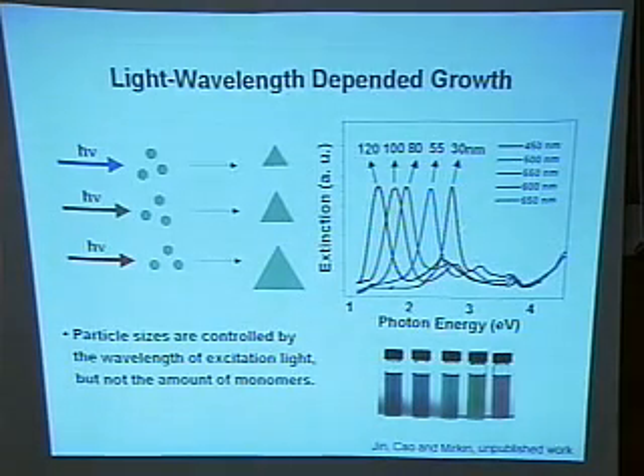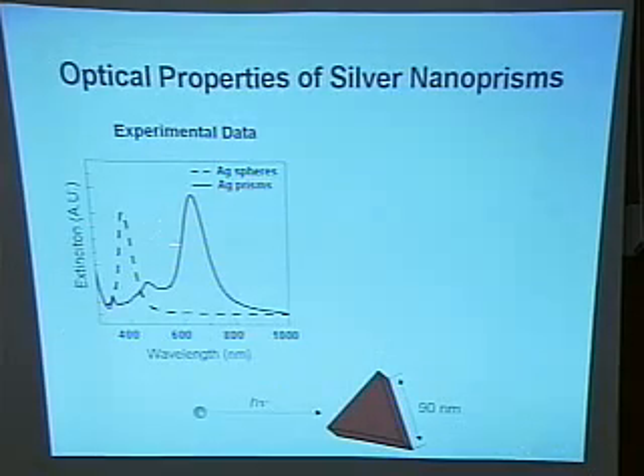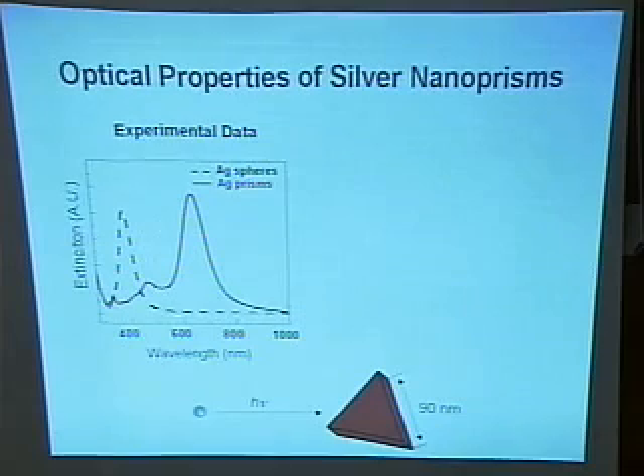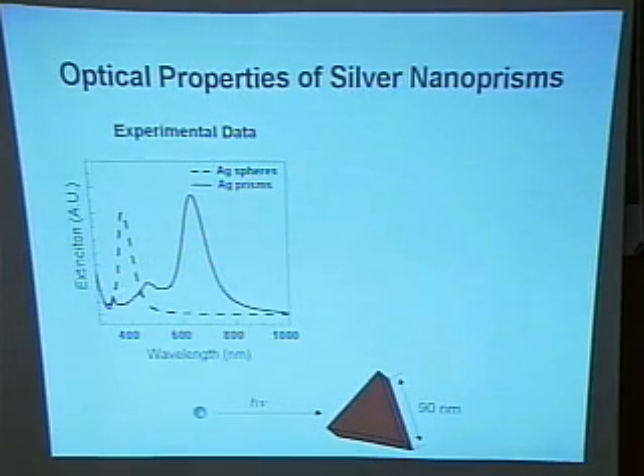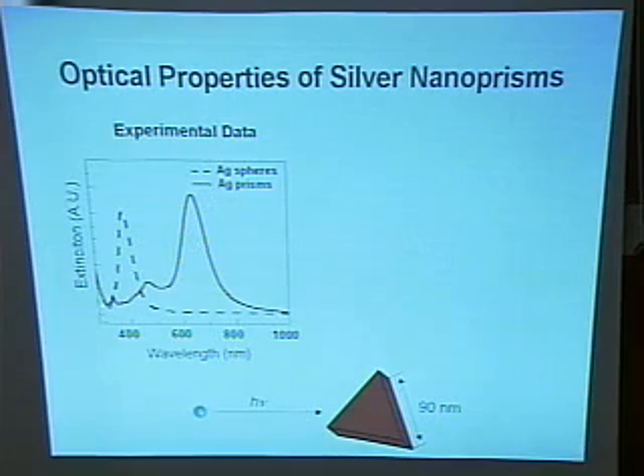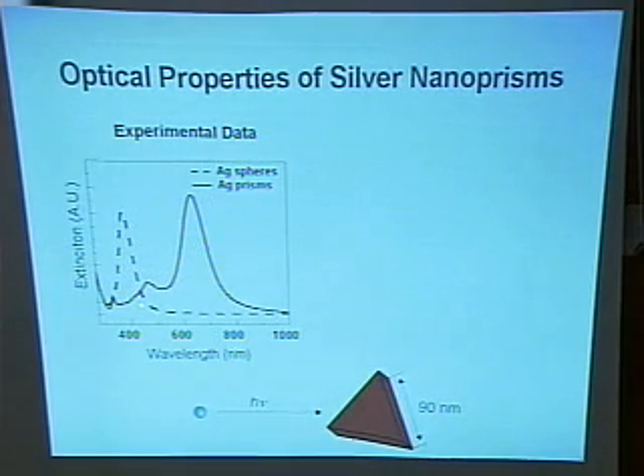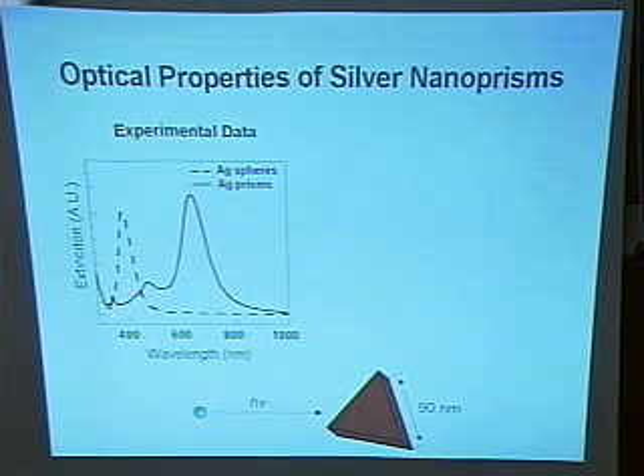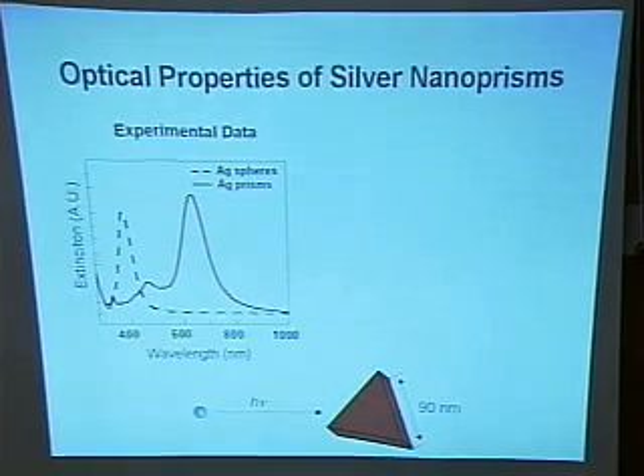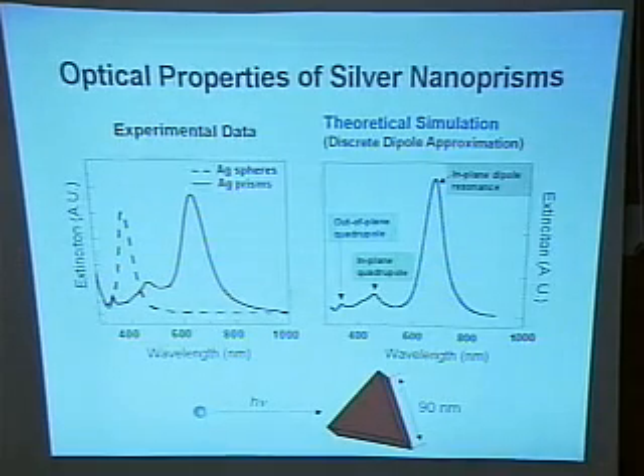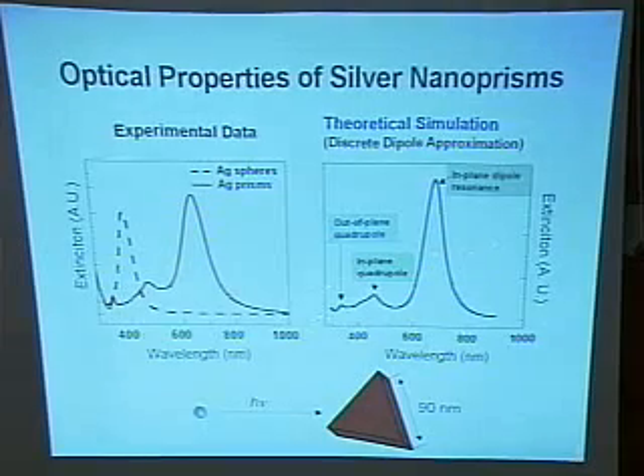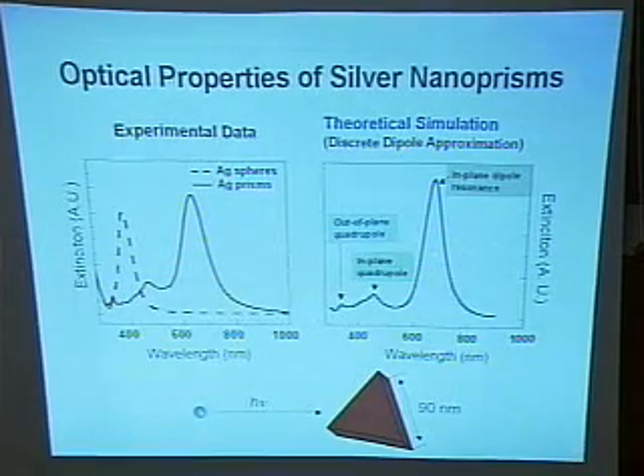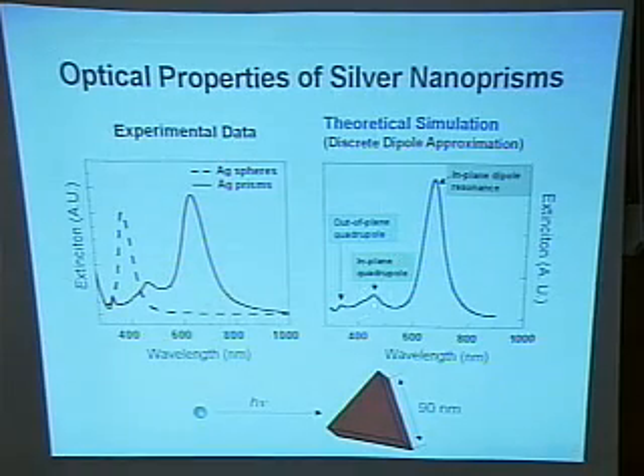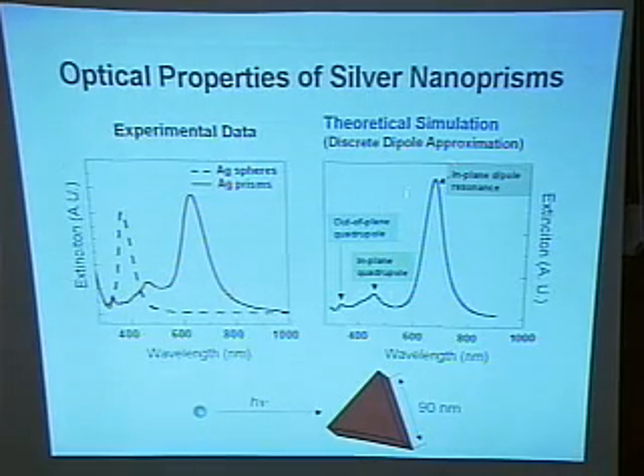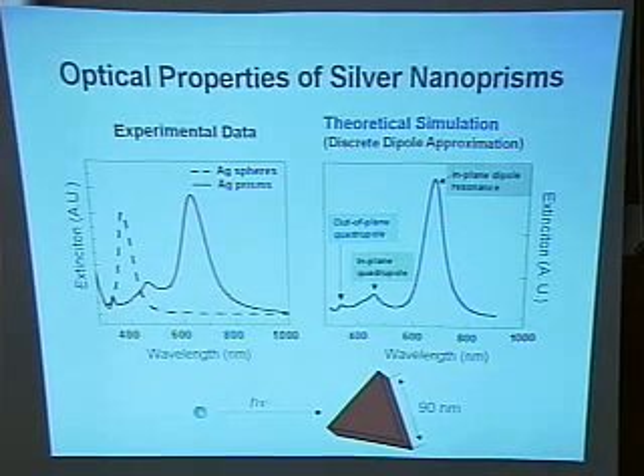Then the next thing we have to understand is the optical properties of each nanoprism. What is the meaning of these peaks? Here I will show you the experimental result compared with the spherical particles. You see, the nanoprisms have 3 peaks, which is totally different from the starting point. What is the meaning of this small peak and this larger peak? We carried out a theoretical calculation, using discrete dipole approximation. We found the first small peak is the out-of-plane quadrupole resonance, and this peak is the in-plane quadrupole resonance. The big peak is the in-plane dipole resonance.